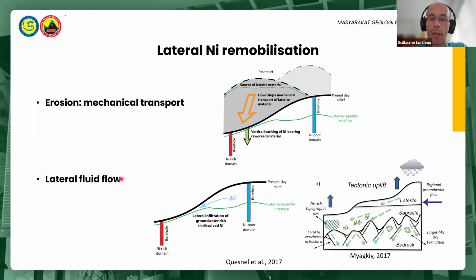The second process consists of lateral infiltration of groundwater rich in dissolved nickel from high topographic areas to downslope areas. These processes, combined with the preferential development of saprolite in uplifted areas, may be responsible for higher grade of slope deposits. So it's a complementary process.